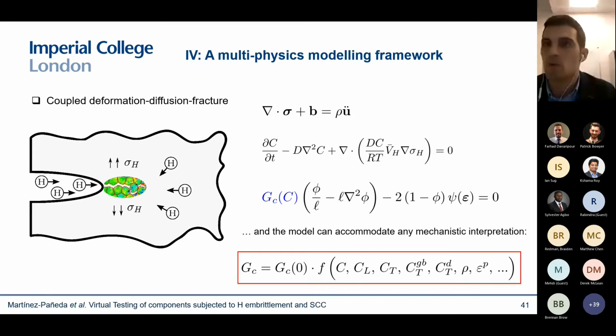Well, the good news is that this is a universal framework. It can accommodate any mechanistic interpretation. You can define this degradation function as a function of the total hydrogen concentration, the lattice hydrogen concentration, the hydrogen concentration in grain boundaries, the dislocation density, or many of these variables. So it can accommodate any mechanistic interpretation. And I emphasize this because there has been also a little discussion in the literature, in the hydrogen-assisted fracture literature, regarding different mechanisms and the role that they play in different materials and environments. And I think this is important to know, that you can accommodate whatever you want.